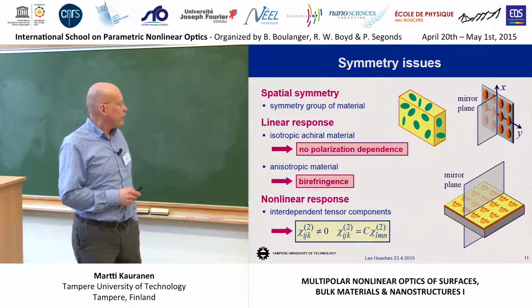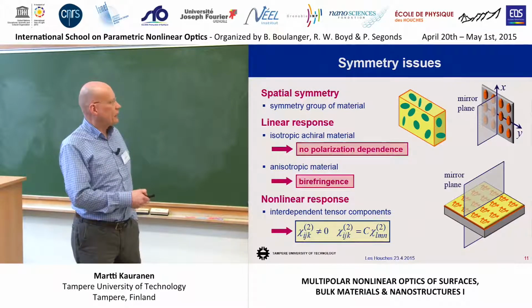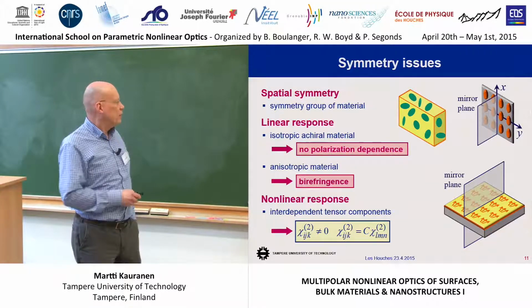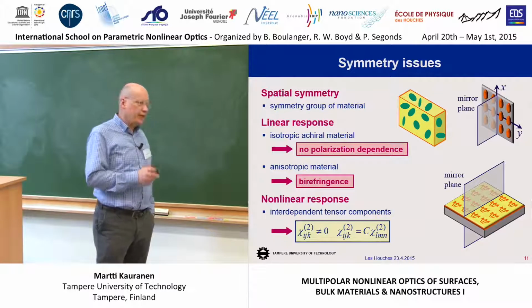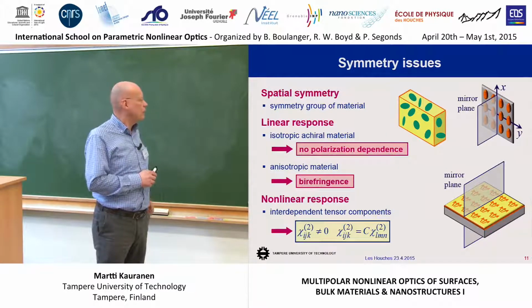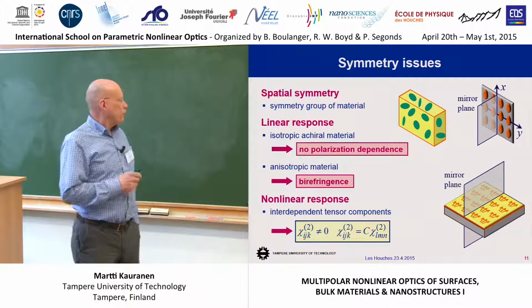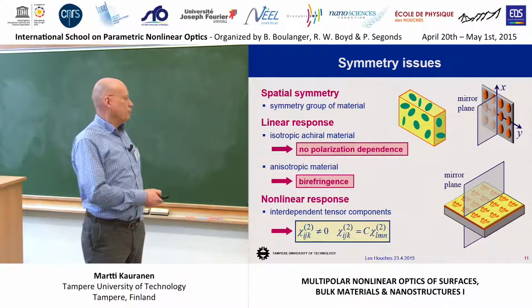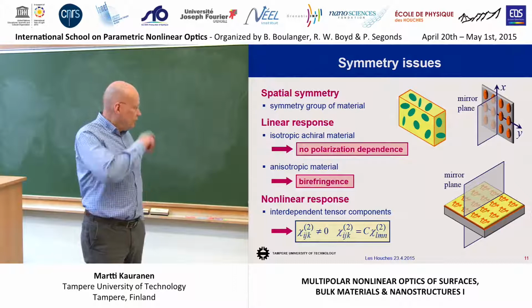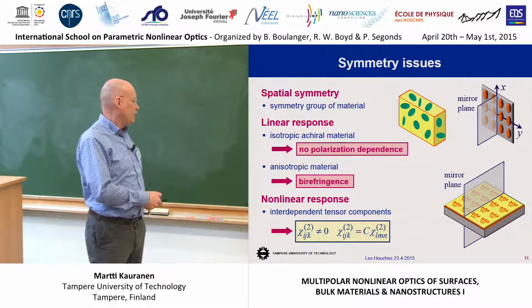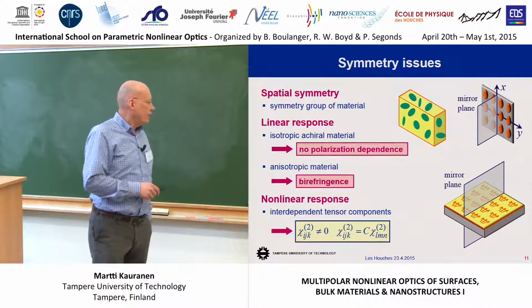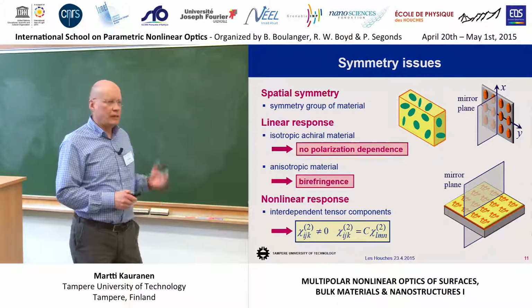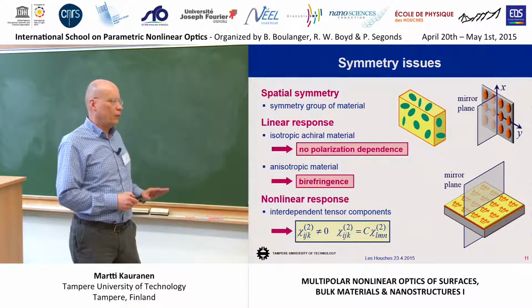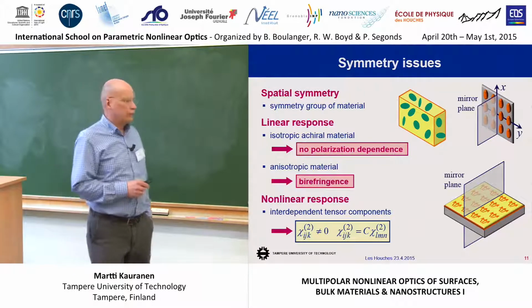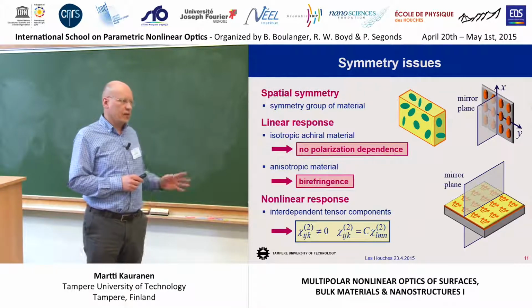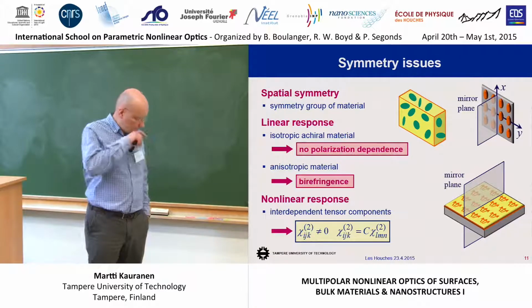However, if the material is anisotropic, then the response in, let's say, x direction can be different than in y direction, and we get birefringence, and if you look at the absorptive part, we get dichroism. And then, if you look at nonlinear response, we look at all the possible symmetry operations. Then, with some luck, we can usually kill a number of the tensor components. And if we cannot kill them, we can find that certain tensor components depend on each other. They could be equal with an opposite sign. There could be a factor of square root of 2, square root of 3, or things like that, depending on the symmetry group of the material.